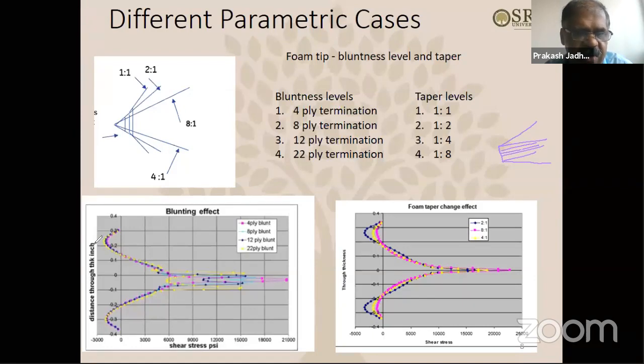Different results in the sense that if you monitor this interlaminar stress variation through thickness, you can see that due to the different ply termination, the stress level at the tip is varying. Also, as you change the taper of this tip here, the taper level also has an effect, and you can see the maximum interlaminar stress level is varying at the tip. Okay, so going ahead.